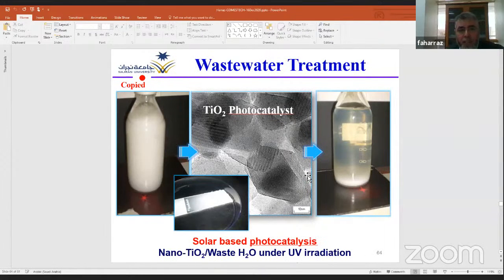This is just pictures copied using photocatalysis in wastewater treatment. This is the titania photocatalyst as a thin film. And this is a very nice example of solar-based photocatalysis under UV radiation. The point is that titania is the most widely used semiconductor photocatalyst. However, due to its wide band gap energy, around 3.2 electron volts, it absorbs only a very small portion of the solar light, around 5%, and it operates in the UV regime.